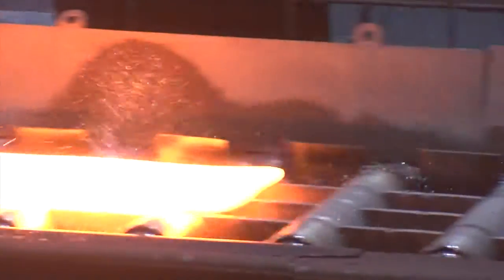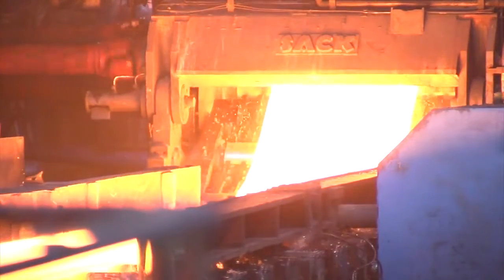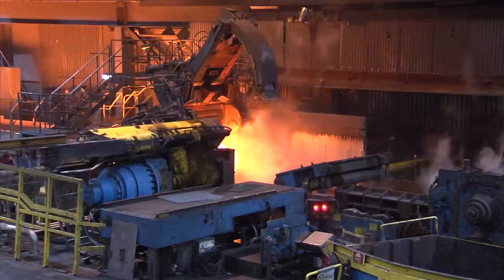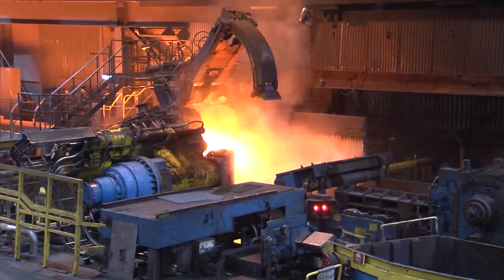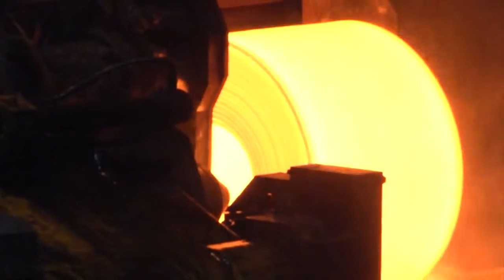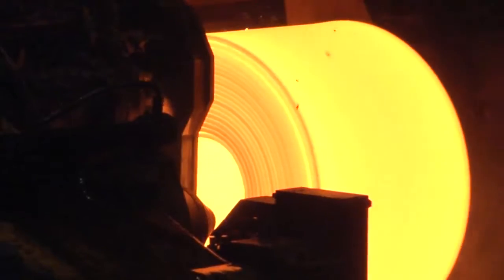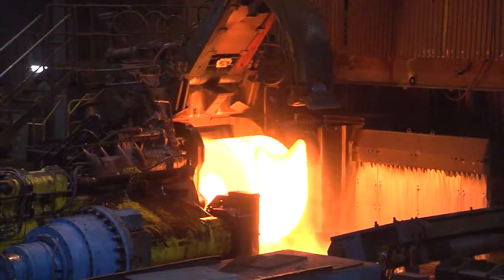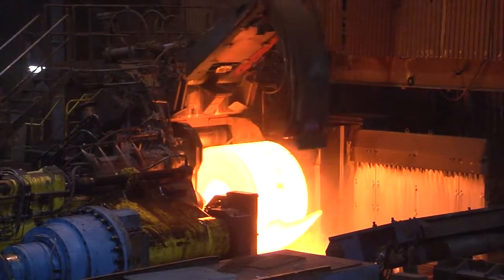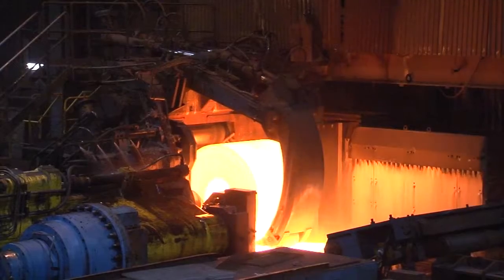After the roughing mill, the transfer bar is rolled up in a coil box. The coil box's primary purpose is to save space, but when inside the coil box, a temperature equalization also occurs. The temperature difference between the ends of the material is minimized as the transfer bar is coiled together. When the transfer bar is removed from the coil box, it has a temperature of about 1050 degrees centigrade.